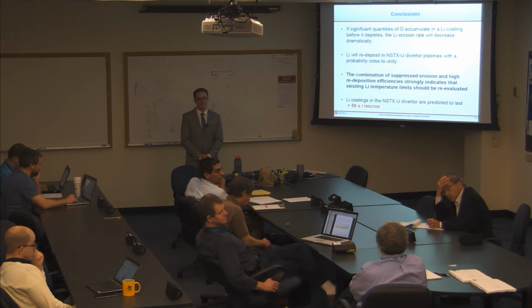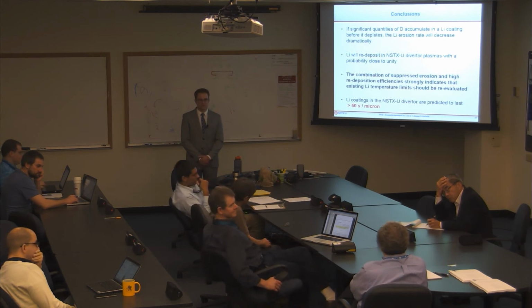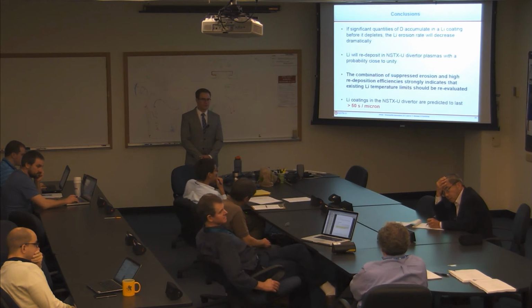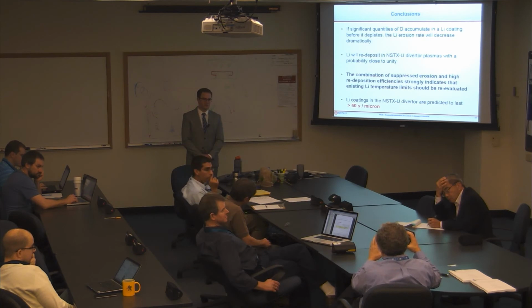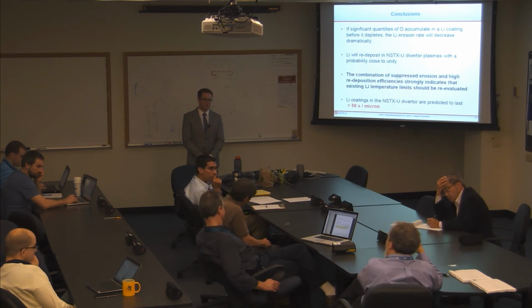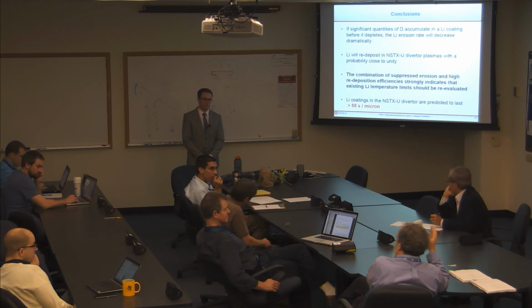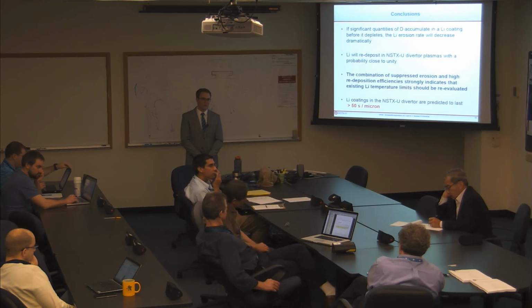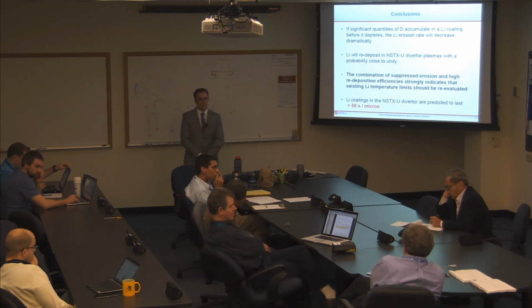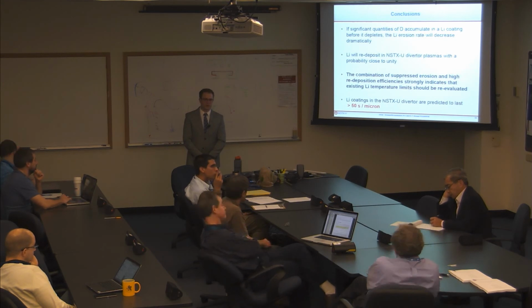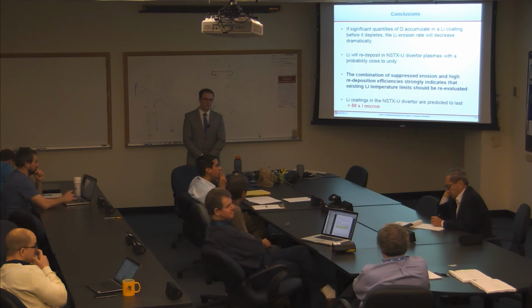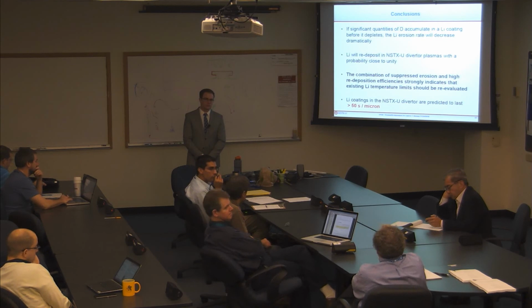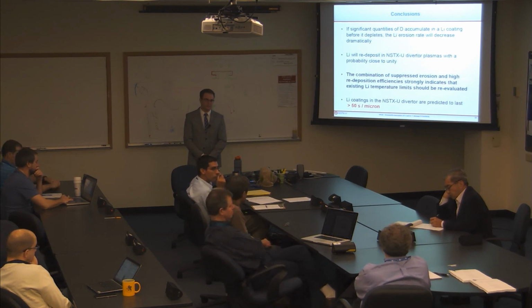So essentially what you're saying is that this stuff is altering into lithium deuteride, and so it doesn't evaporate as much as you might have otherwise thought. Yes. But then you told us that lithium deuteride has a melting temperature. Sure. I'm actually just trying to put bounds around this to understand it a little better. There's some temperature range over which this should be a big effect, but then I would think once lithium deuteride melts, those bonds don't count anymore, then it would return to being the evaporative limit. That you would approach the evaporative limit. That would have to be investigated, and you'd have to get up to 700, 800 C to investigate that. But you think at the 500 C level, where people have been moaning about, oh my God, too much lithium, they may be missing by a couple orders of magnitude at this point. Exactly. Yeah. Excellent.